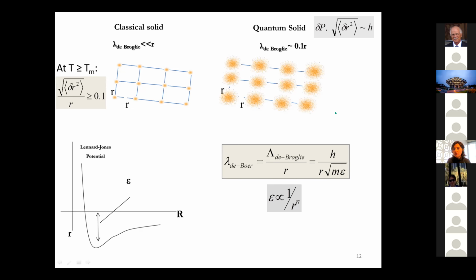And it turns out if you use this uncertainty principle and play around a tiny bit, we can see that the de Boer parameter in materials is going to be proportional to R to the power of n over 2 minus 1, where n is the type of interaction. If you have a very short range interaction, we have 1 over R to the, I don't know, 12. If you have a very long range interaction, n is small. And obviously for a large de Boer parameter, we are looking for lighter stuff, because this is 1 over the square root of mass.